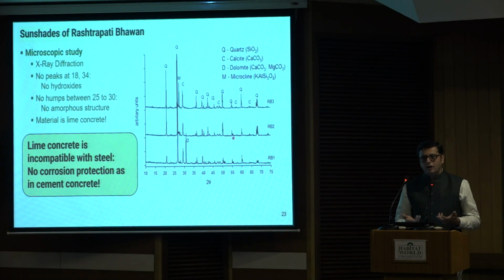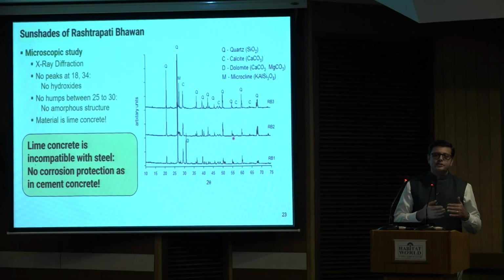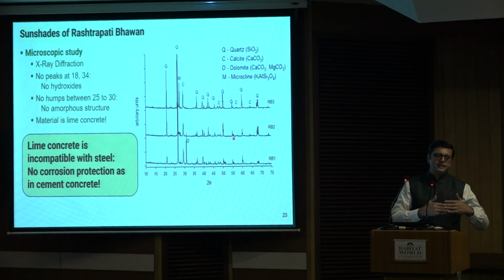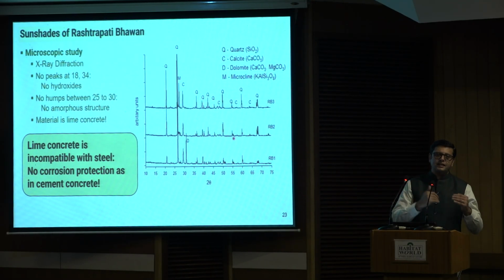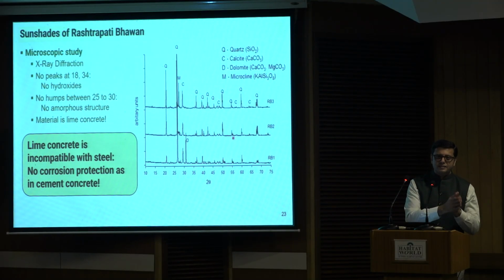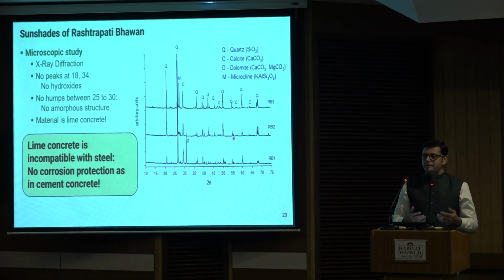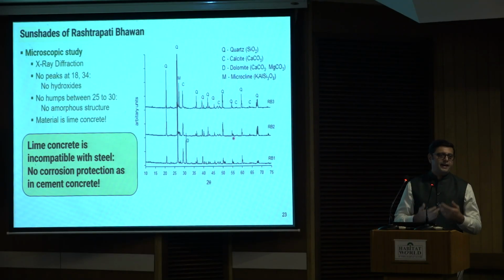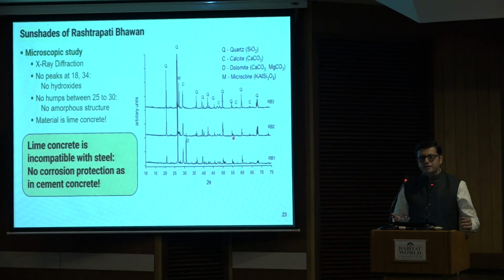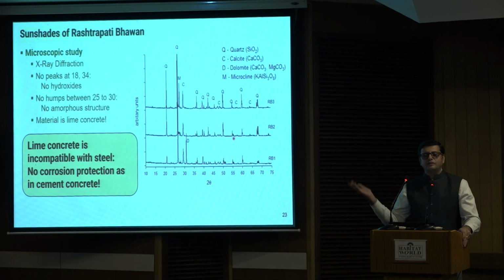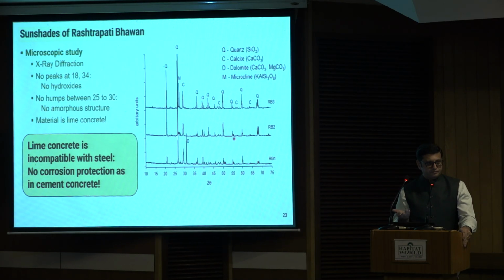And the problem with lime concrete is that it does not create what is called a passivating layer that prevents moisture and air from reaching steel. Lime is highly porous and allows moisture and air to reach the steel. And that was really the reason why, in about 85 years, the entirety of the sunshades had corroded.